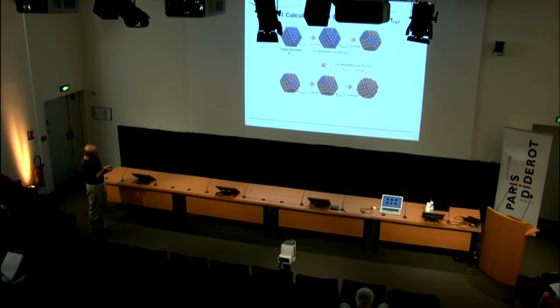Now we start with this structure and we put one atom on the triangular, 111 surface. The energy for adsorption of that is minus 3.07 eV. So that energy is a little bit weaker, and that's a little harder to do, but once that first one's on there, all of the others are easier, with more negative energies. So as soon as I put this first atom on here, it makes it easier for the second, third, fourth, fifth atom to go onto that facet. That's what the calculation says.